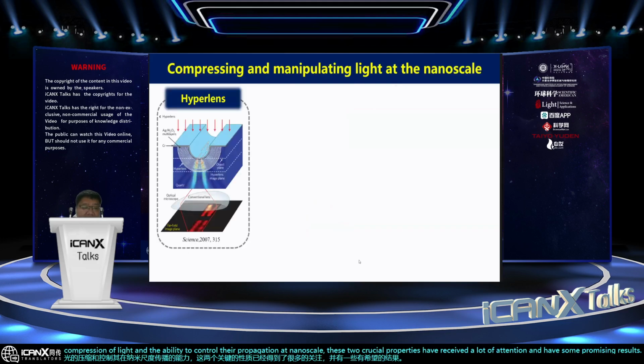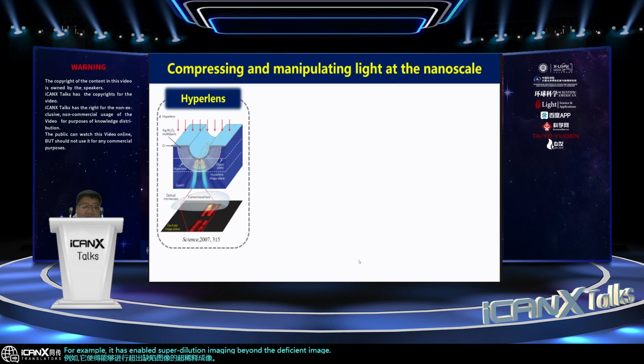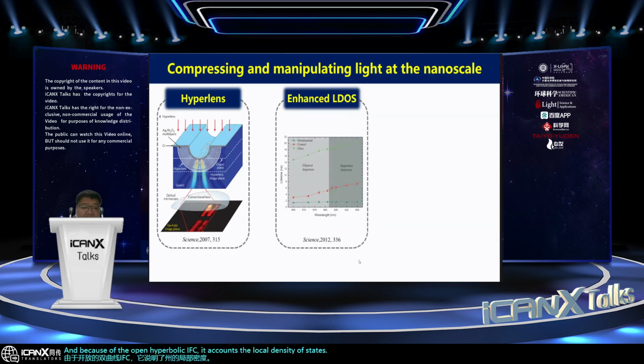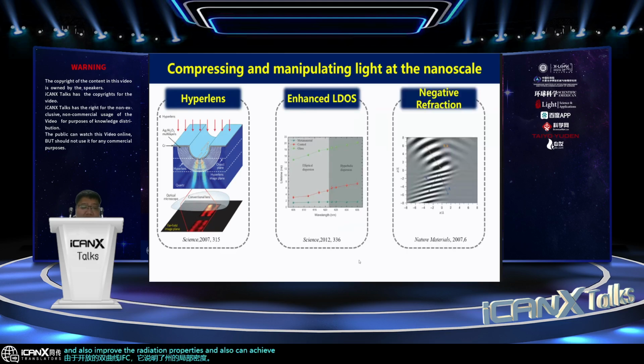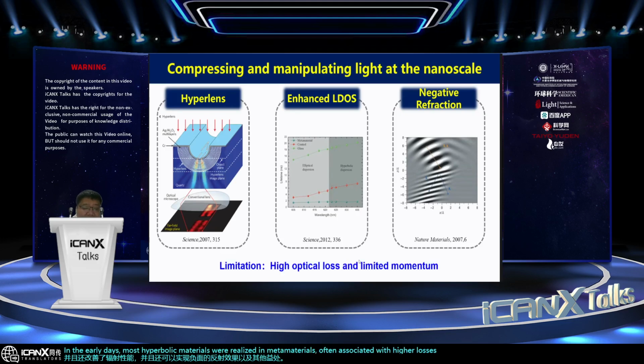For example, it has enabled super resolution imaging beyond the diffraction limits. And because of the open hyperbolic IFC, it enhances the local density of states and also improves the radiation properties and also can achieve negative refraction effects among other benefits. In the early days, most hyperbolic materials were realized in metamaterials, often associated with higher losses. Additionally, the ability to compress light fields was limited by the minimum size of the artificial unit cell, which hinders their